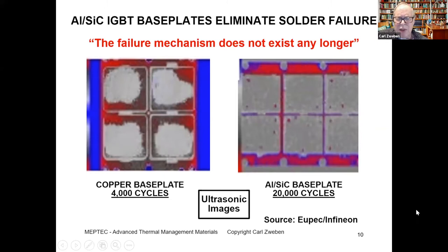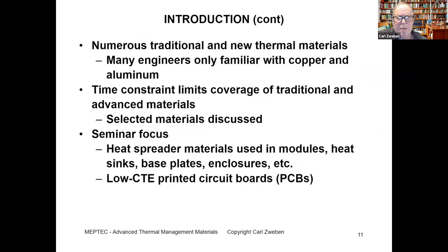And on the right, we have the AlSiC base plate after 20,000 cycles. And as you can see, with copper there's a failure of the solder attachment, but there's no failure of the solder joint with the AlSiC base plate. And the authors of the paper concluded that the failure mechanism, which is fatigue cracking, does not exist any longer.